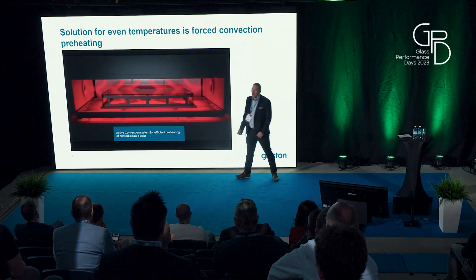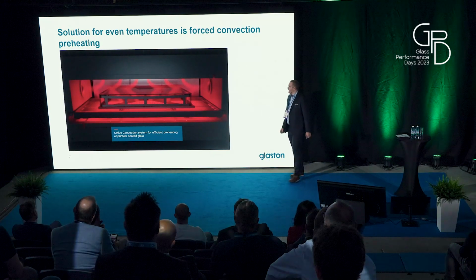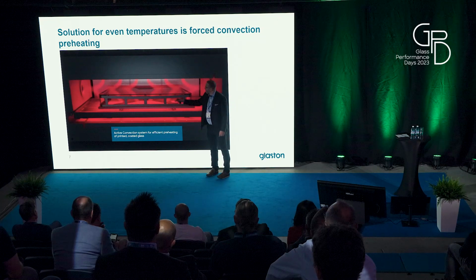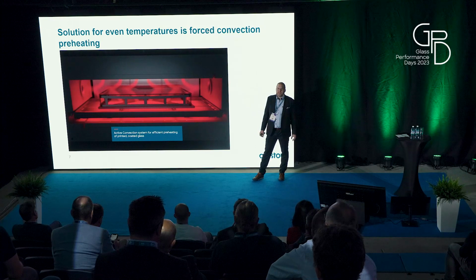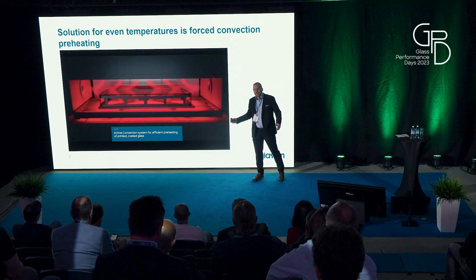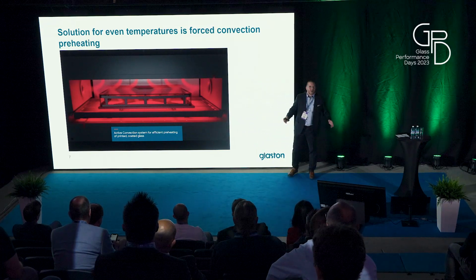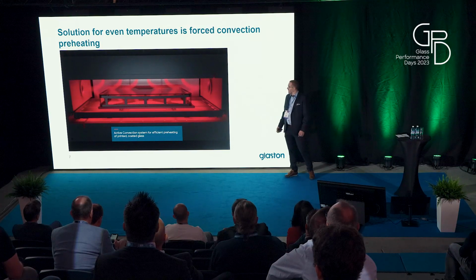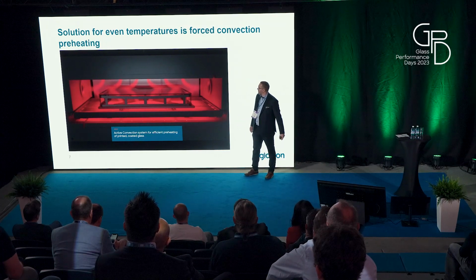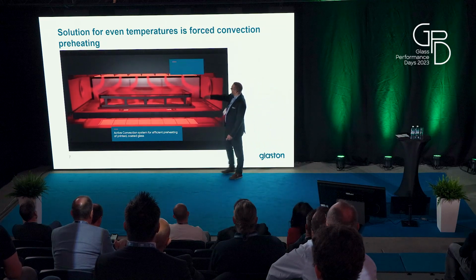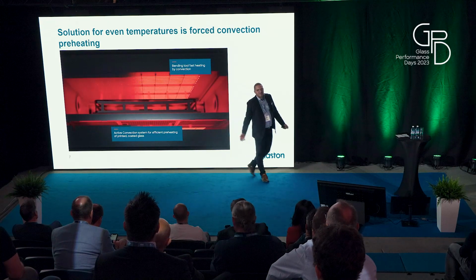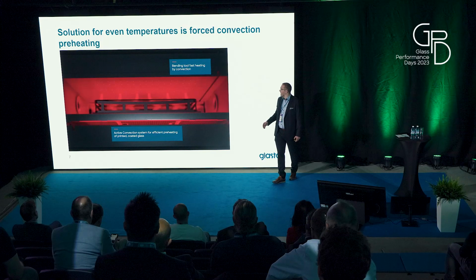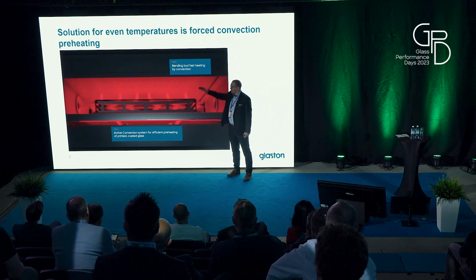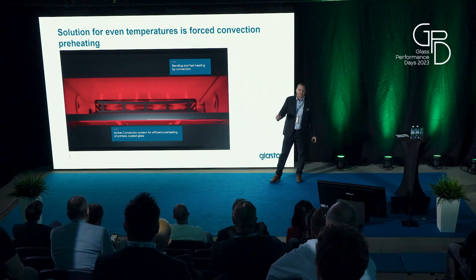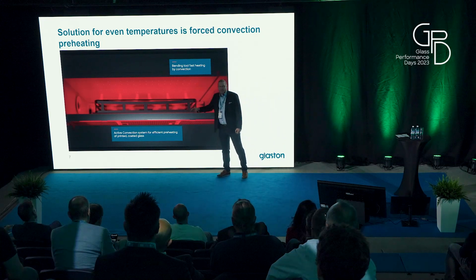So here is how we have solved this, how our convection heating part looks. This is one of the chambers in convected heating. You saw before that there might be, depending on the line, 5 to 10 or 20, depending on how much production you want to do. Here's one animation where we can see a couple of advances that we have made. Basically, there are heating elements at top and bottom to get the heating done. But we have put a cover on top of those heating elements so that you don't get straight radiation from the heaters to the glass surface, but there is some metal sheet in between to balance this radiation.